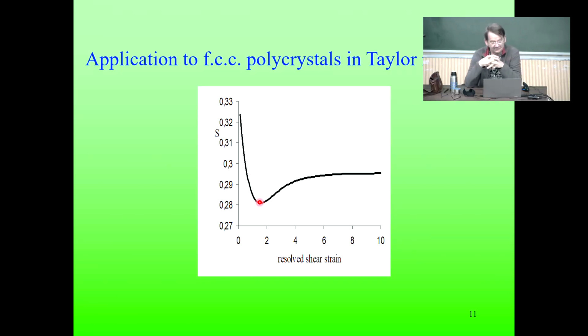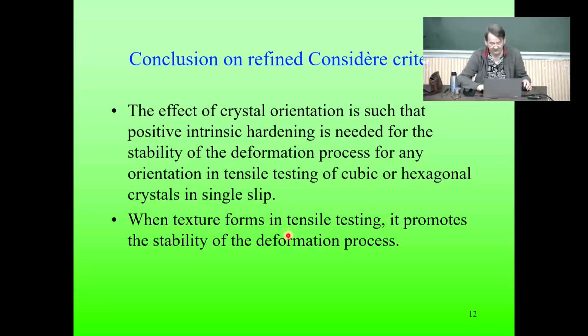So good news that crystallographic slip doesn't make it worse. It is helping the stability of the deformation. Basically, what happens is that the crystal rotates into a better orientation for stability. Yes, this point is the classical Considère criterion here for isotropic material. So this is showing how, in tensile testing, an FCC polycrystal in Taylor modeling is going to contribute to the stability of the deformation. Okay.